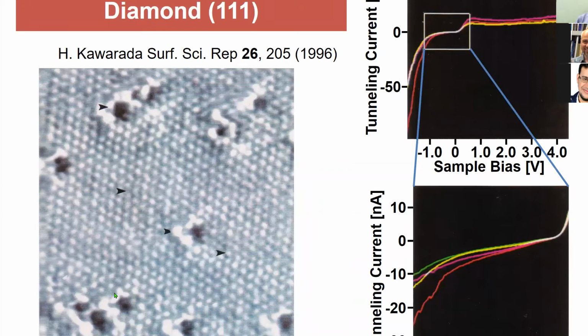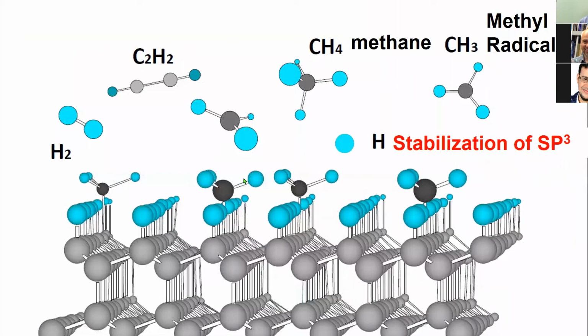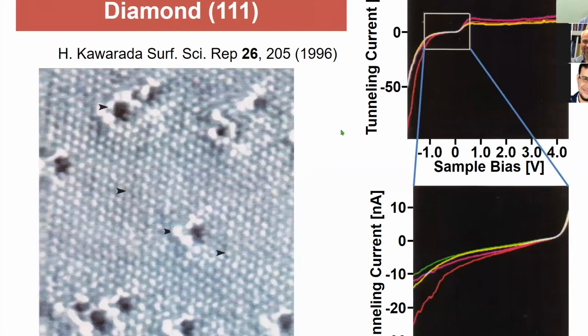But after taking many pictures, what we found is that this is the remaining of those methyl or hydrocarbon layers, which are going to start a new layer. So this is not a defect, but I think this is a precursor, or some kind of diamond island, to get another layer. This surface is very interesting from a point of view, because it already has p-type nature.